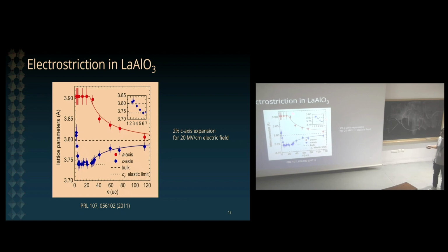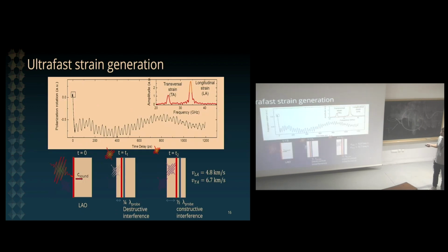I like to illustrate it with the example of lanthanum aluminate on strontium titanate. A few years ago, we did this experiment at a synchrotron facility where we showed that because of electrostriction, lanthanum aluminate undergoes a 2% lattice expansion with an electric field of the order of 20 megavolt per centimeter. That's a pretty big change. So lanthanum aluminate undergoes this electrostrictive phenomenon. What happens when we are exciting the system at resonance?